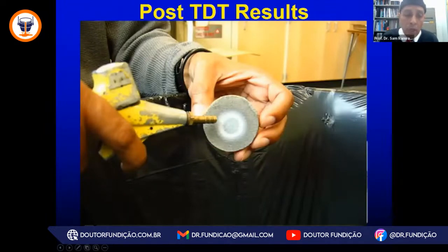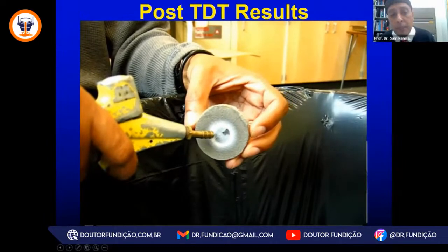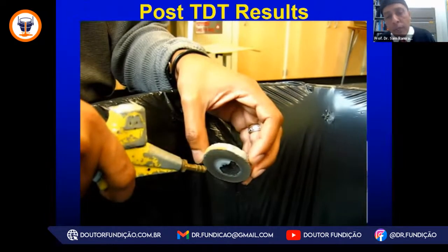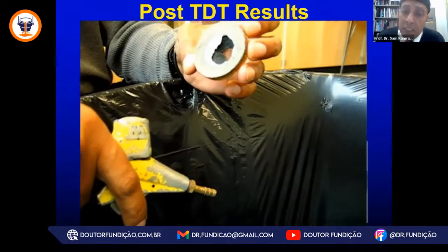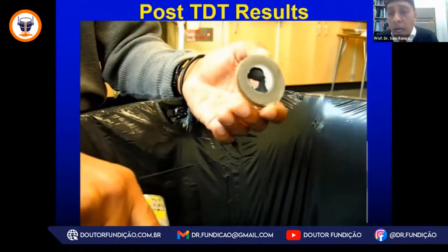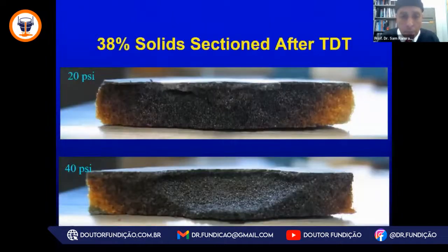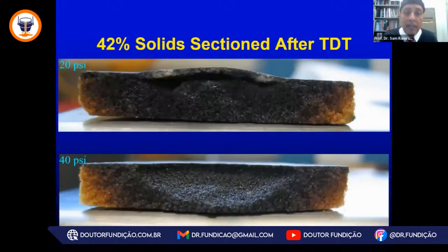And here, if I blow the coating off that sand on this test specimen, you will see the pyrolyzed sand falling away. We have collected that sand and we have measured the LOI, and we know that there is 40 to 60% of that chemical binder still on that pyrolyzed black sand. It's still there. So with the coatings, we have to choose the right solids levels that we place on the sand as well. Here we have blown the coating off with 20 psi pressure, 40 psi pressure, and we have measured again the amount of binder left after thermal experience for a 38% solid and a 42% solid.